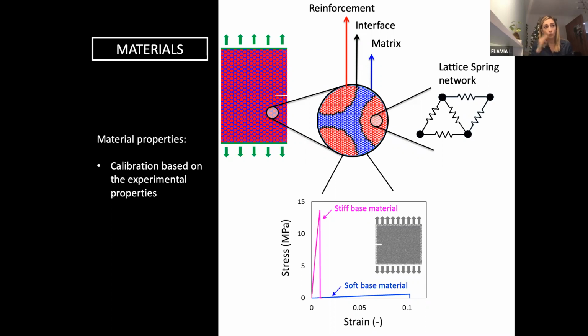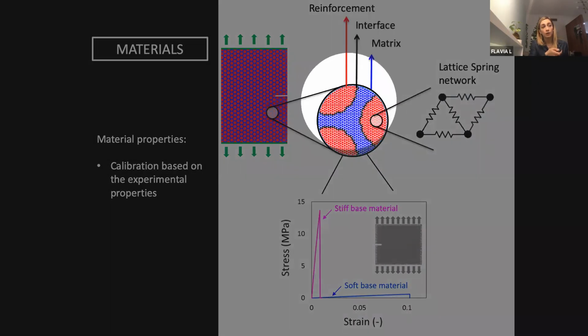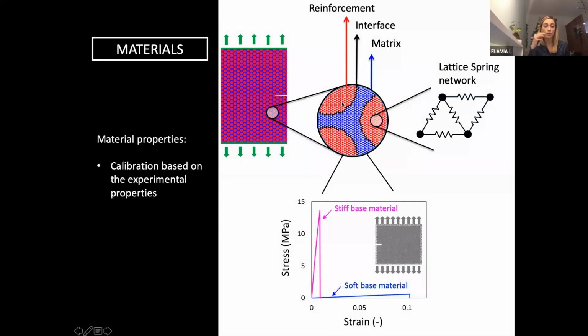So why did we have to do this calibration in a systematic way? Well, because once you print this material, and this is very important for the printing technology, you actually have two materials at the beginning. We use a PolyJet technology with a multi-nozzle printer, where you have different nozzles jetting these materials in more or less a liquid form, and the materials are then UV cured immediately.